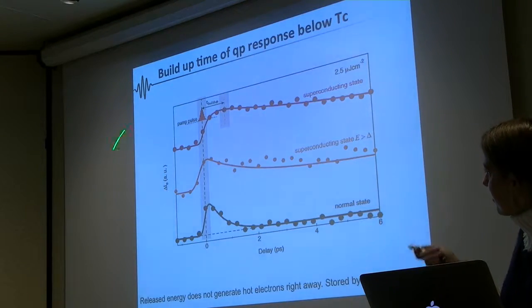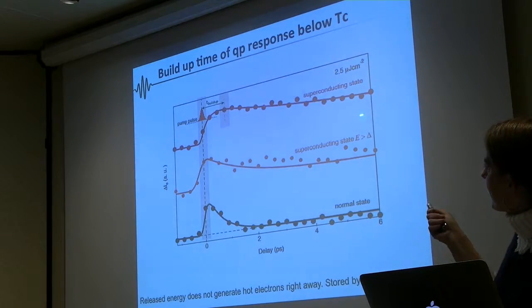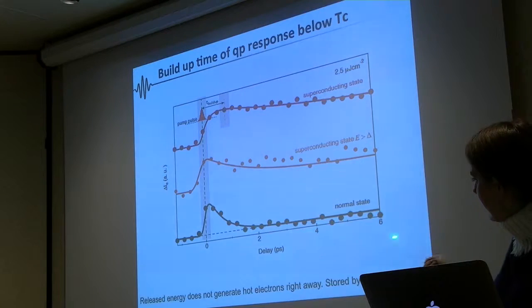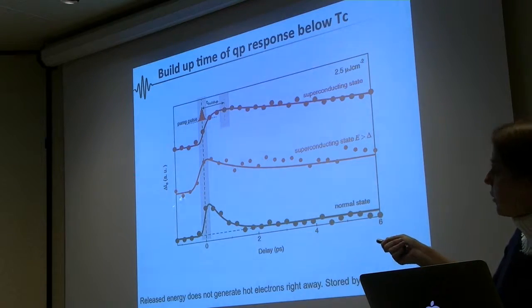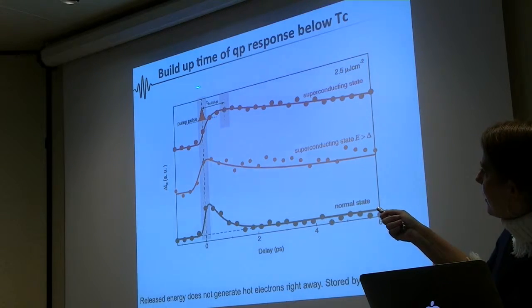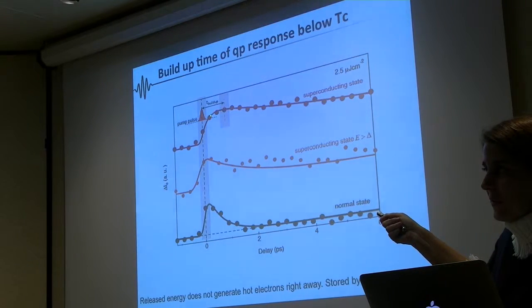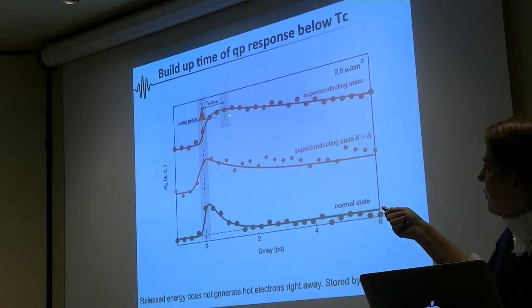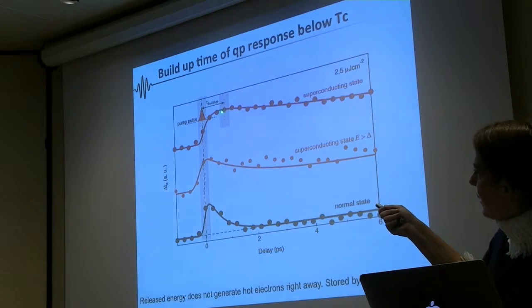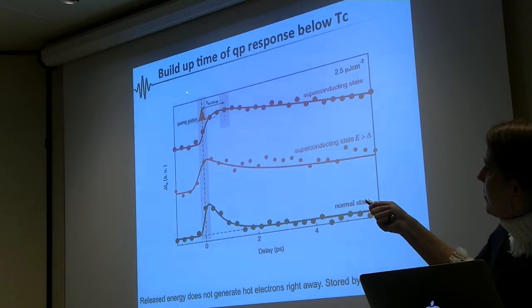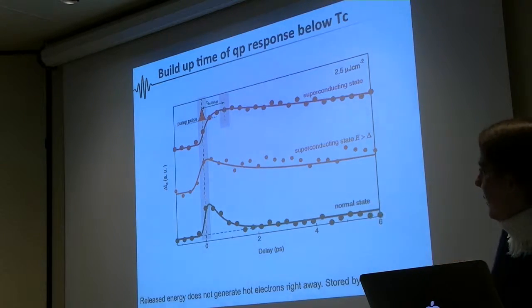And so here is the interesting thing. What we can do is the experiment in the superconducting state. And these are, again, zoom-in data. Here we're looking at the intensity. So I go back to look at the intensity, and you see that there is this delay in the response, which is not what was predicted or measured or learned before with optical experiment. There is this delay here. And this is what we call now a build-up time.